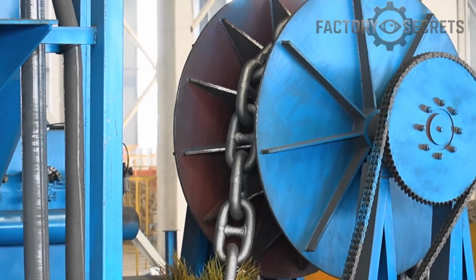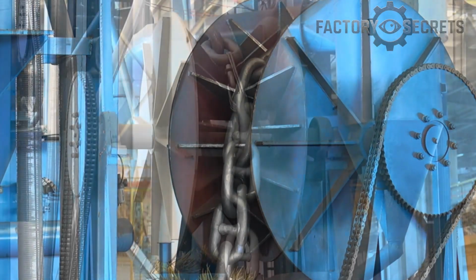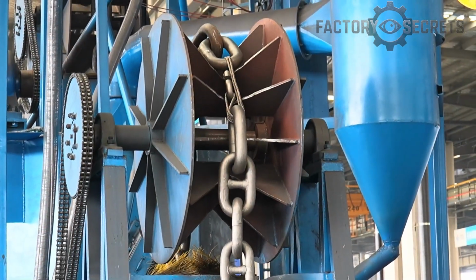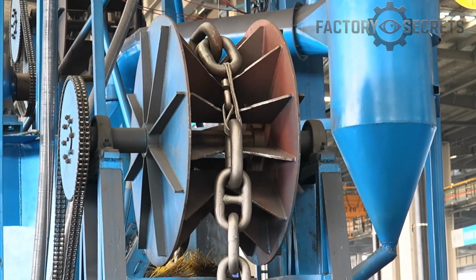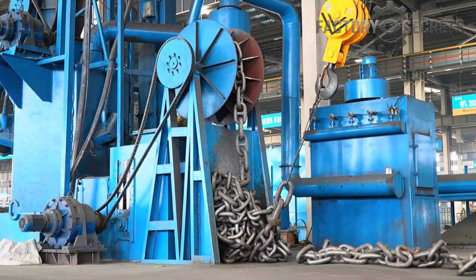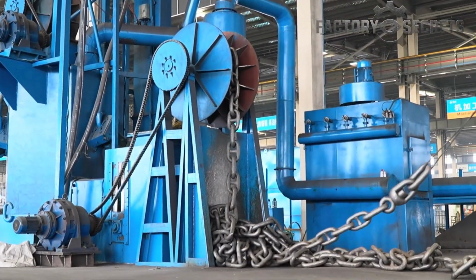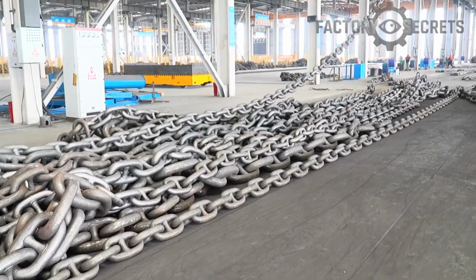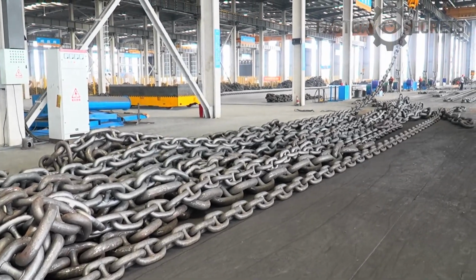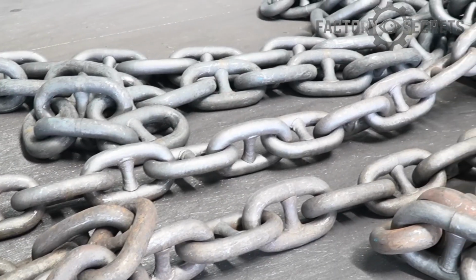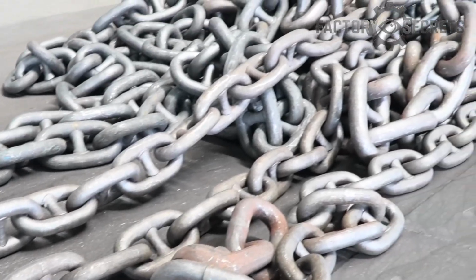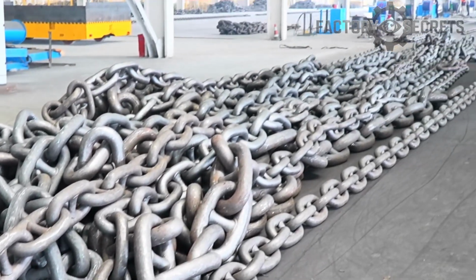But more importantly, shot blasting isn't just cosmetic. It relieves surface stress, improves adhesion for coatings, and reveals any surface defects that might have been hidden beneath scale. The chains are then grouped in the open yard alongside other finished batches, a landscape of steel loops lined up like soldiers ready for deployment.